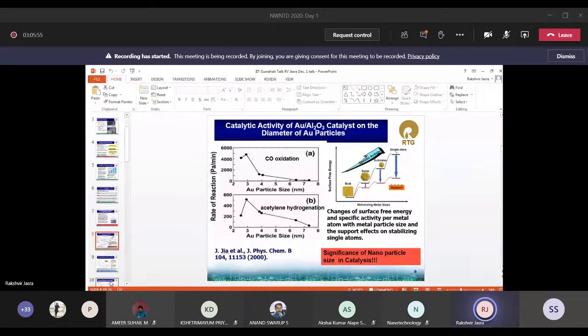Now I'll show you a few examples of how the size of a particle can really influence activity. Here I have shown you a gold on alumina catalyst, and if you see, the moment you go to 3 nanometer size of gold, 3 to 4 or less than 4, the activity rate of the reaction is very high. It really goes up exponentially.